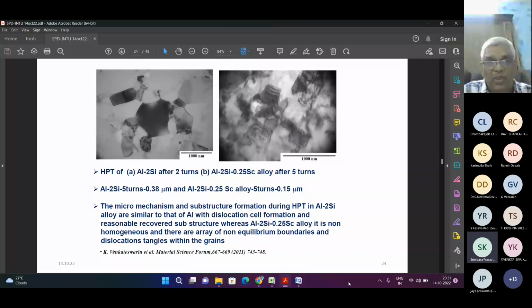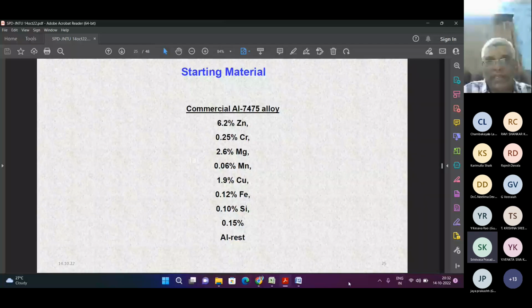The micro mechanisms and substructure formation during HPT in the aluminum 2 silicon alloy are similar to those in aluminum, with dislocation cell formation and a reasonably recovered substructure, whereas in aluminum 2 silicon 0.25 scandium it is non-homogeneous, with arrays of non-equilibrium boundaries and dislocation tangles within the grains that can be measured. So you can understand not only the influence of high pressure torsion after 5 turns, but also the influence of scandium content. This is the work we have published.